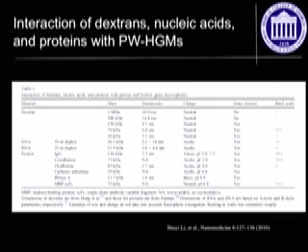We have tested different biological reagents. We have tested dextrans, nucleic acid. We have tested different sizes of proteins. Interestingly, all the proteins that we tested, of different sizes, can internalize, same as nucleic acid. For the dextrans, if their size is too big, they cannot internalize. And some of these biological reagents show specific binding to the wall.